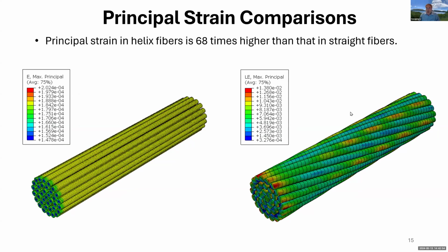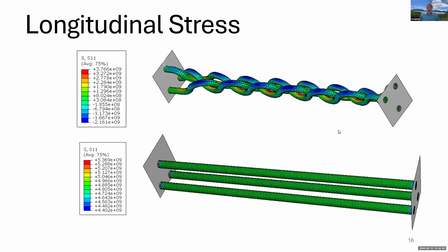And the principal strain, again, is 68 times higher in the helical fiber than in the straight fibers. Recently, after attending a workshop last month, we are trying to see if we can further change the fiber bundle configuration, for example, braiding the fiber rovings into some pattern, as compared with the straight fiber pattern. Actually, this morning, we have the first modeling result.